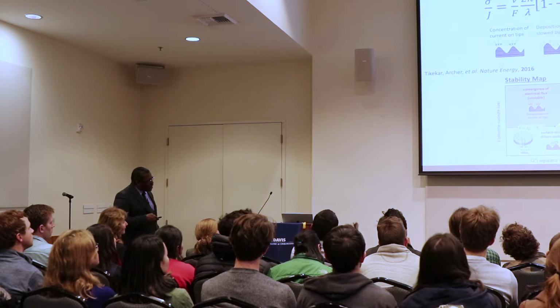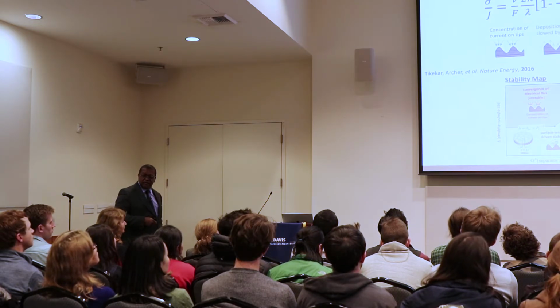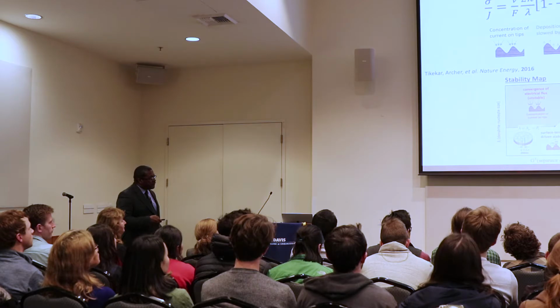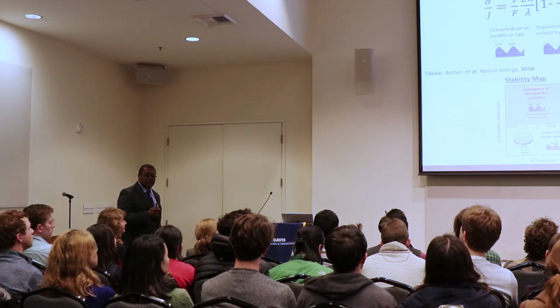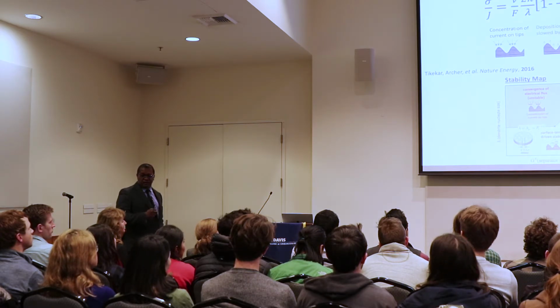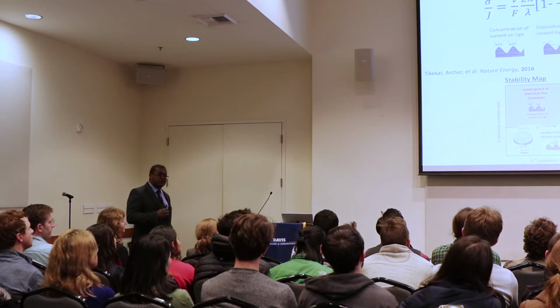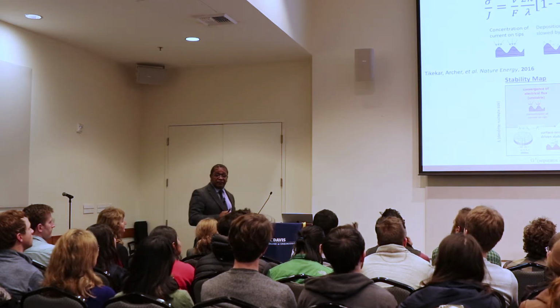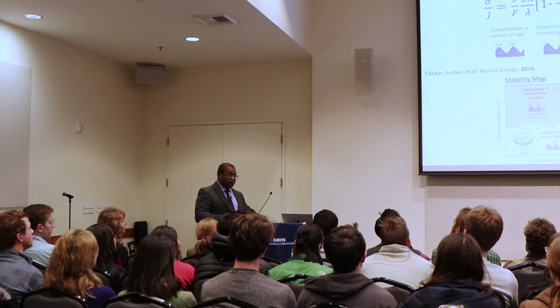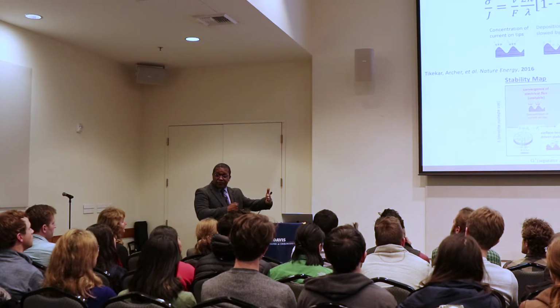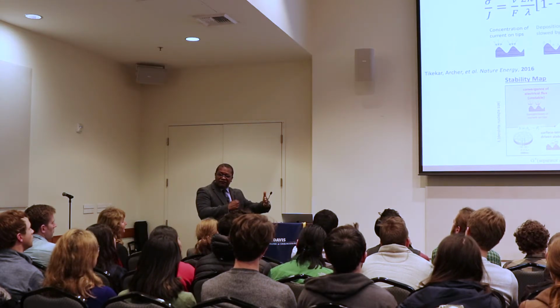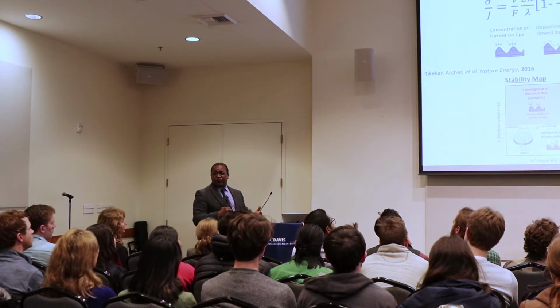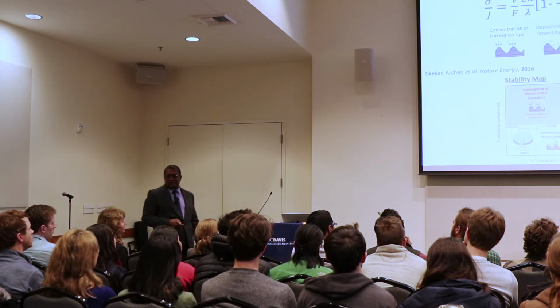Well, the regions in white are basically regions of stability. The surprising result for the field is that we can get stability in this model at any modulus of the membrane. The field normally thinks you need a solid state battery to stop these dendrites, because you need the modulus of the membrane, the separator or electrolyte, to be large enough so that these bumps can't grow through it. What this is saying is, not necessarily.